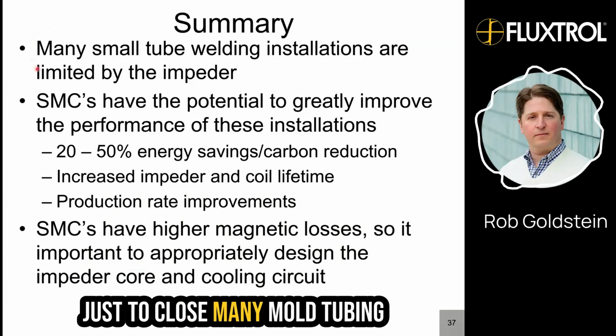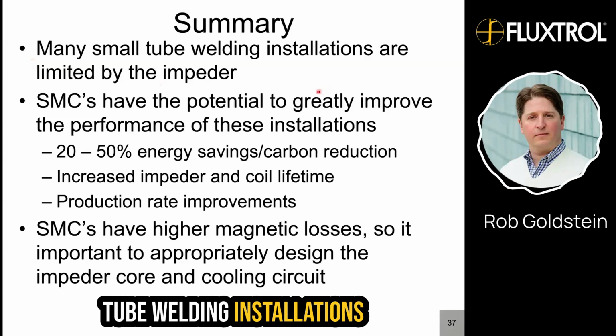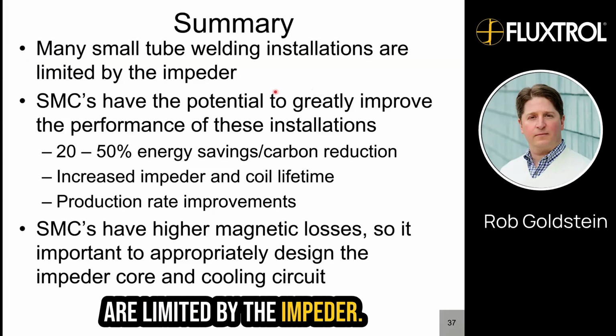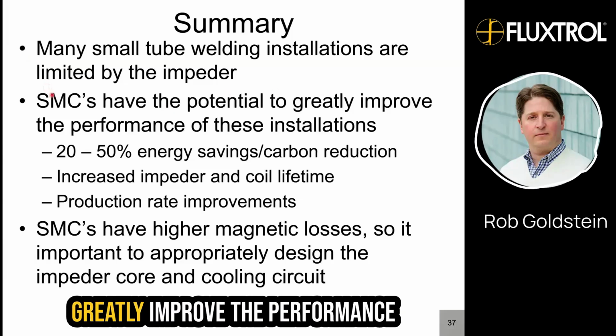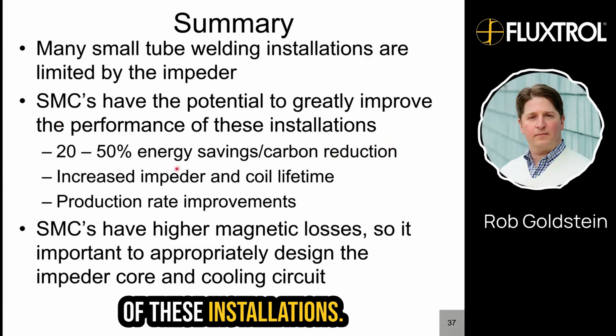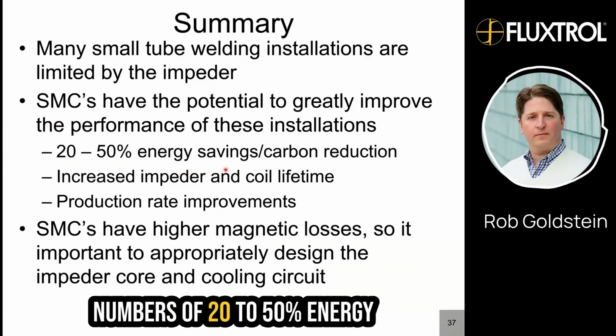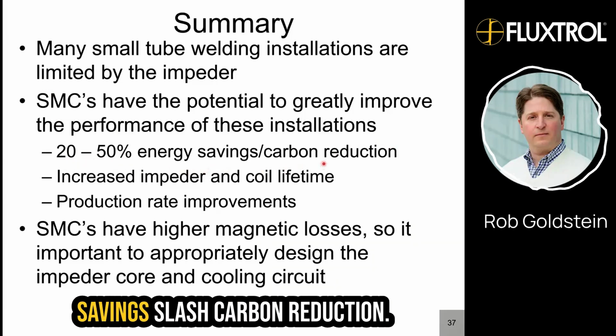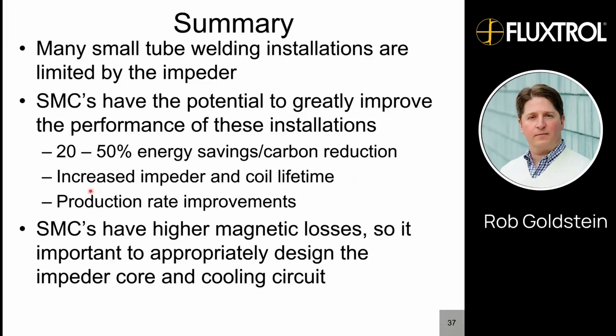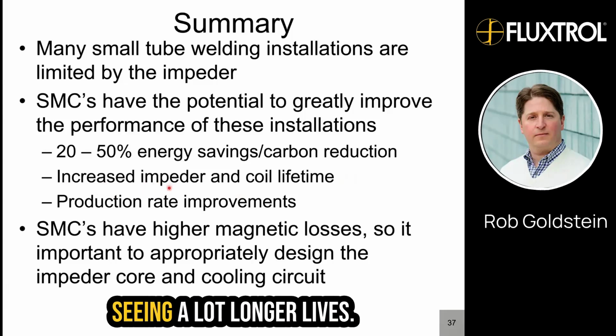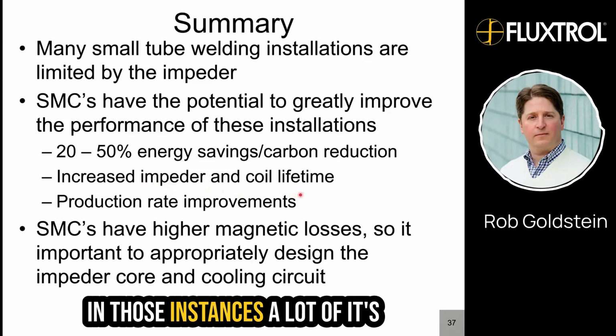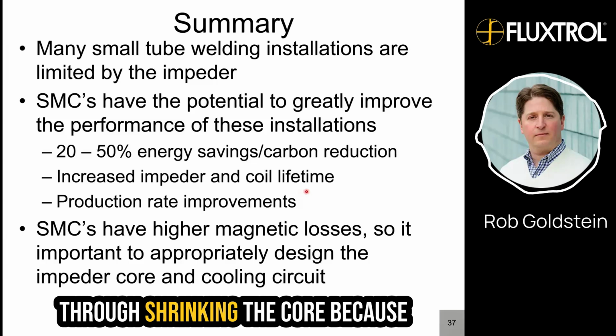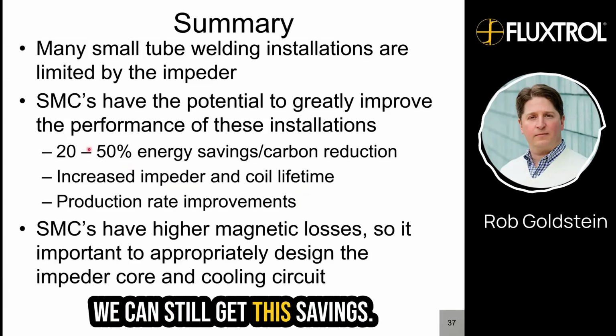Just to close, many small tube welding installations are limited by the impeder. SMCs have the potential to greatly improve the performance of these installations. We're getting pretty consistent numbers of 20 to 50% energy savings and carbon reduction. This is a big one that we're seeing a lot longer lives in those instances. A lot of it's through shrinking the core, because we can still get this savings.